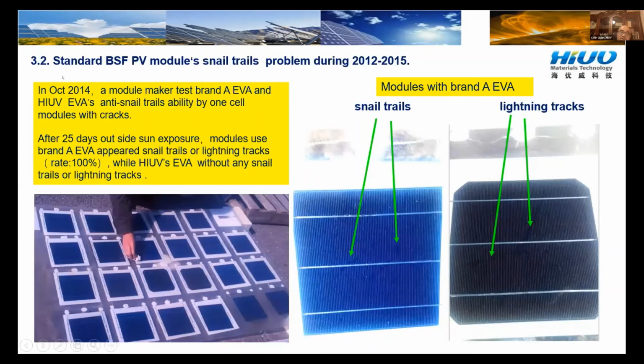So that is another module maker. They did the test by themselves in October 2014. They made a module, tested one brand, and compared it with HIUV for anti-snail trail ability, using one-cell modules with glass on top. On the top is one piece of glass. On the bottom, they selected several pieces of cells with cracks, and laminated them with a slightly bigger back sheet. They connected it by itself. They put it just outside for 25 days of sun exposure. The module using brand A's EVA appeared with snail trails and the lightning track like here.